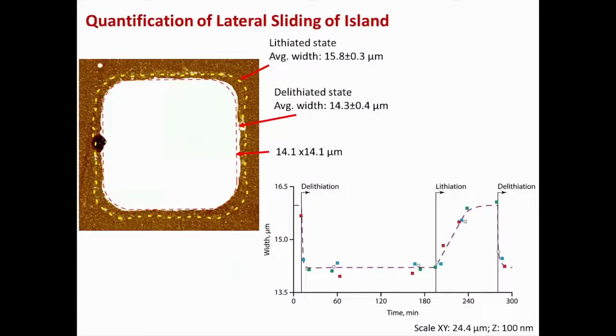One thing of main interest here is the lateral sliding of these islands, because this sliding of the islands is what is putting the strain in the SEI layer. So what you can see is that this sliding is on the order of 1 to 1.5 micrometers, which results in about 10% lateral expansion of the whole island size.